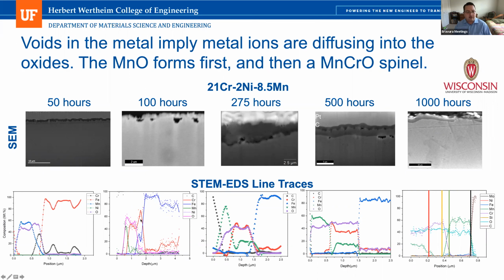Now, as we go on to longer time, we still have the manganese oxide, but now that spinel is starting to be much larger than the manganese oxide. And that continues on. We also start to see the formation of a chrome oxide, and it's most evident here. So we have the manganese oxide, and then we have a depletion of manganese. So we just have chrome and oxygen. So we have a chrome oxide layer, then we have the spinel layer, and then we have the metal.